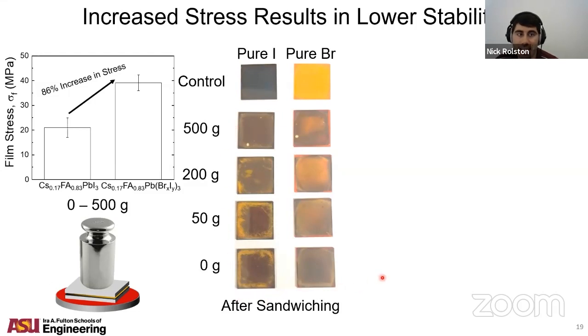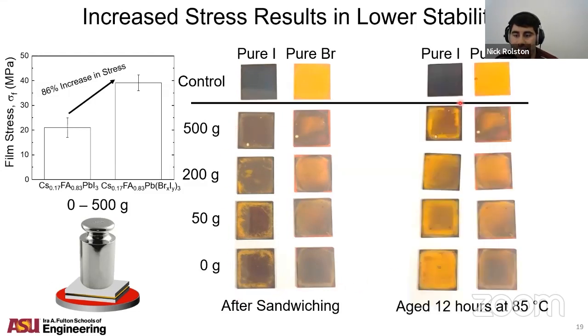But the challenge is, because there are higher stresses after they're aged at high temperatures, you can see that they all start to degrade much more noticeably than the controls even. So this is showing that this approach was not really effective.